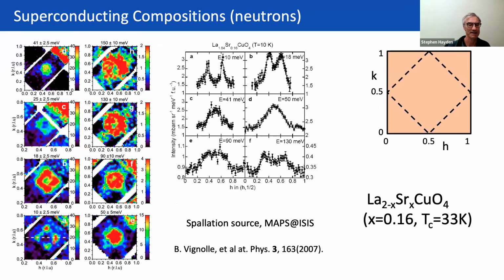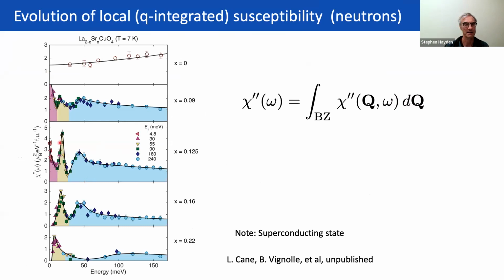Well, I can tell you what, Sabir, I can tell you what we wouldn't see. We wouldn't see a resonance mode because the resonance mode seems to occur at the incommensurate position. So if one was exactly at a 1/2 and came up through this hole in the middle, then you would wipe out this thing completely. Okay. Right, because this feature is due to these 4 peaks, which are slightly away from 1/2, and then this thing here seems to appear.